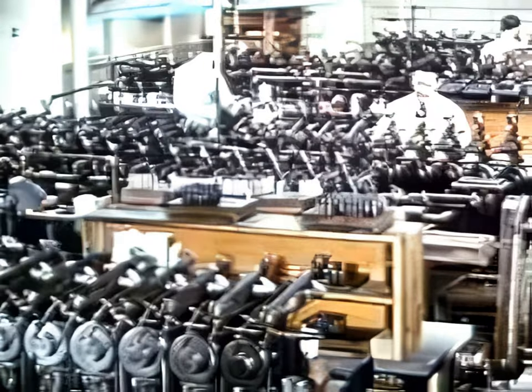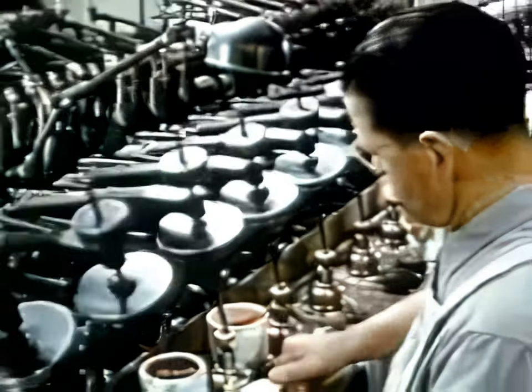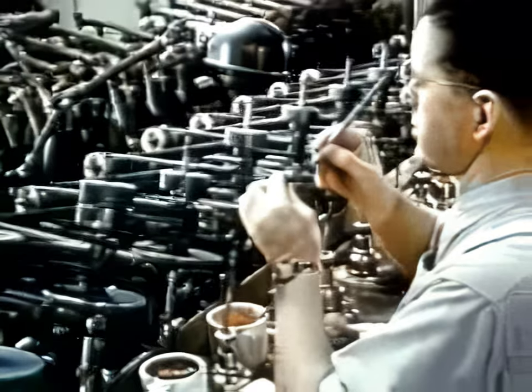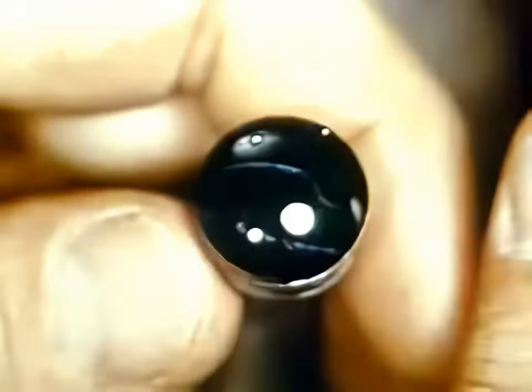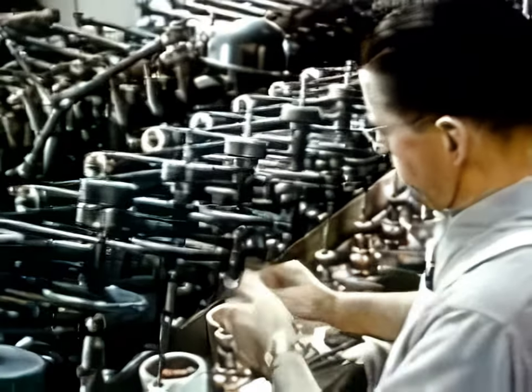Completeness and evenness of polishing is checked by placing a test glass of the exact opposite curve in contact with a lens. When these surfaces meet, a pattern of light rings is formed, each less than a millionth of an inch deviation from perfect. Here's one with six, so back it goes until it checks to three rings or less.